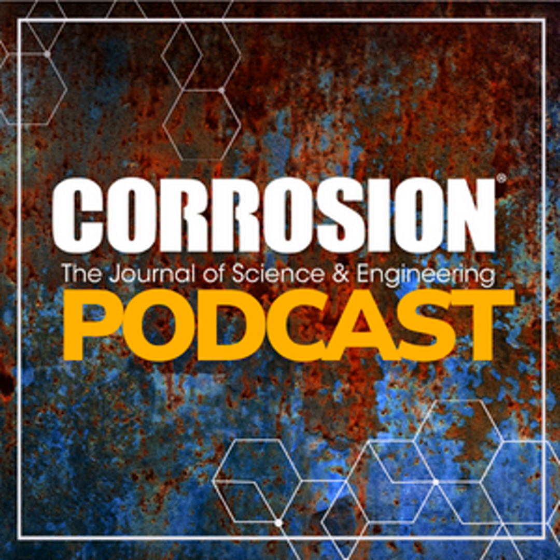We could even observe this by looking at the surface roughening, which we can observe by time of flight SIMS, which of course can be measured directly also by atomic force microscopy, which is one of the specialties of Alain. We could also follow the surface roughening, and finally we can show that there was no formation of a stable complex with carbonate. So this is perhaps something that remains a little bit puzzling, that it seems that carbonate is enhancing the effect of chlorides without reacting strongly with the iron surface.